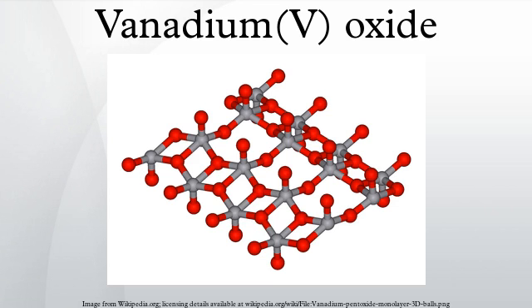The reaction is performed between 400 and 620°C. Below 400°C the V2O5 is inactive as a catalyst, and above 620°C it begins to break down. Since it is known that V2O5 can be reduced to VO2 by SO2, one likely catalytic cycle is: SO2 + V2O5 → SO3 + 2VO2, followed by 2VO2 + ½O2 → V2O5.